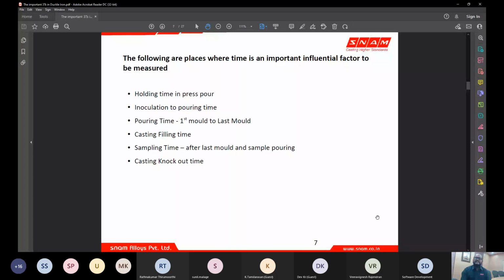And sampling time: people used to take a sample after pouring the last box, or close to pouring the last box. There can be a standard practice in the foundry where you take the sample at the given time every time, such that you can start comparing one heat with the other. And casting knockout time has a surface impact on the castings, where your surface hardness can increase, or your residual stresses in the castings can increase when you knock it out at an early time.